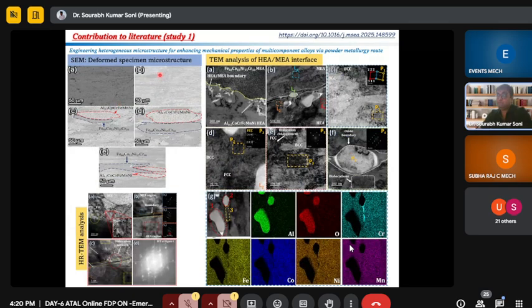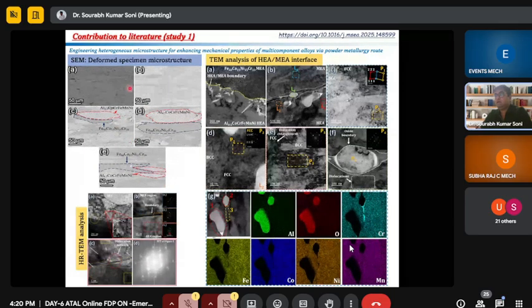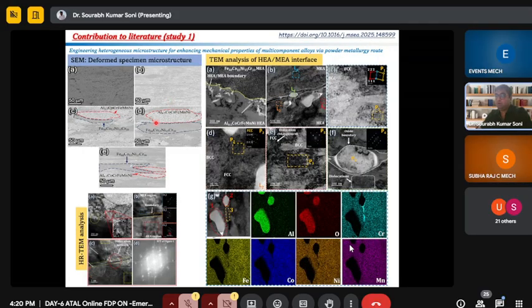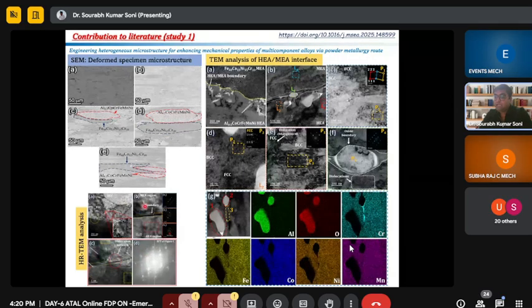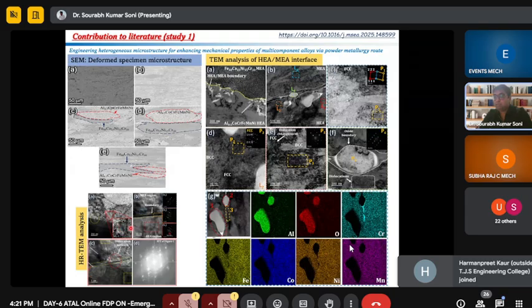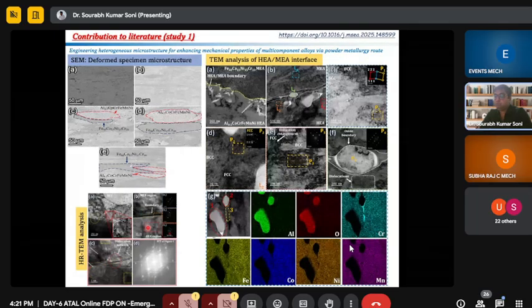This is the deformed specimen showing the microstructure. You can easily analyze what kind of deformation is going on, how much the sample is deformed. And this is the TEM, which is needed nowadays. If you want to publish your data in a high impact factor journal, they are looking for the TEM. So you must do the TEM for your specimen. In this TEM, we are analyzing what is going on at the atomic level, where the oxide is, how the oxide is distributed throughout the specimen, and through HRTEM we can analyze what other oxide particles are available. Like in this HEA-MEA interface, we have observed very novel kinds of oxides which have not been explored until today. So you can find this kind of observation while using the TEM.